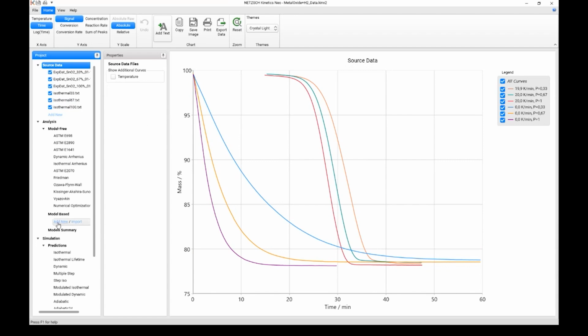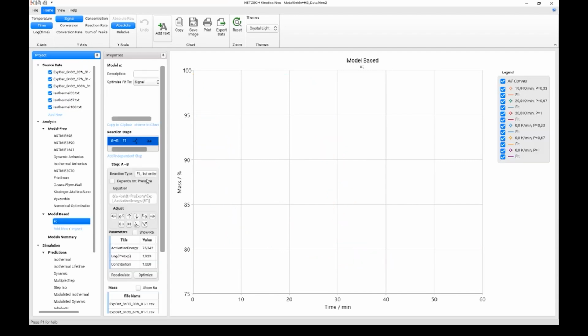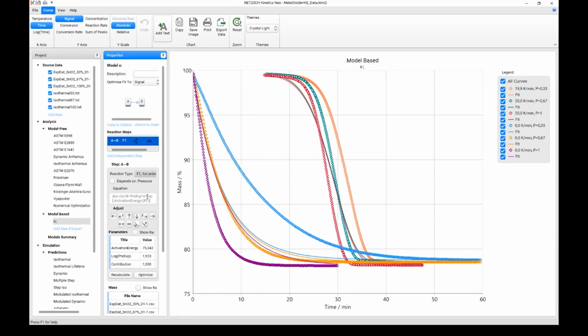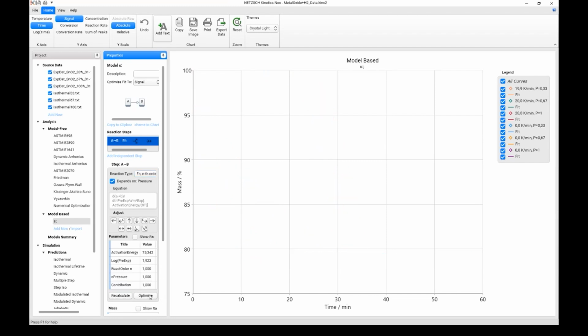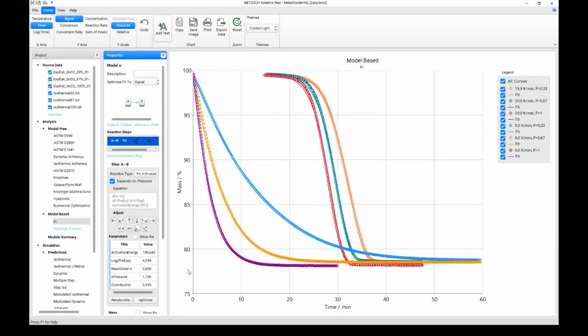Now we have this data, and we will create a model. We select the nth order reaction. For this nth order reaction, we say that the model must have dependence on the pressure. After that, we optimize the parameters. Ready. Now we have a kinetic model which has dependence on two parameters, pressure and temperature. And here are our parameters for this one kinetic model, which can describe all 6 curves.